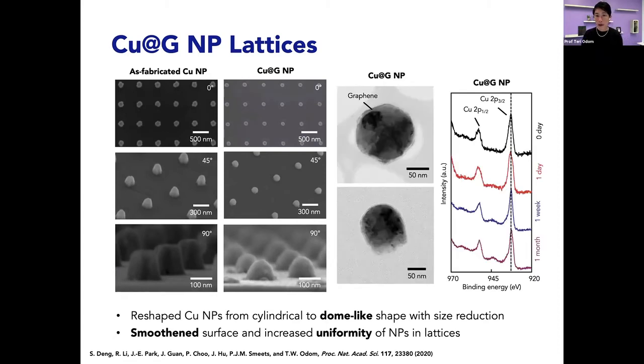And then to ensure the uniformity and conformality of the graphene, we used transmission electron microscopy. And so you can see few layer graphene on the particles. You can see where if we scrape off the particles, there's only few layer graphene on the top, not the bottom.